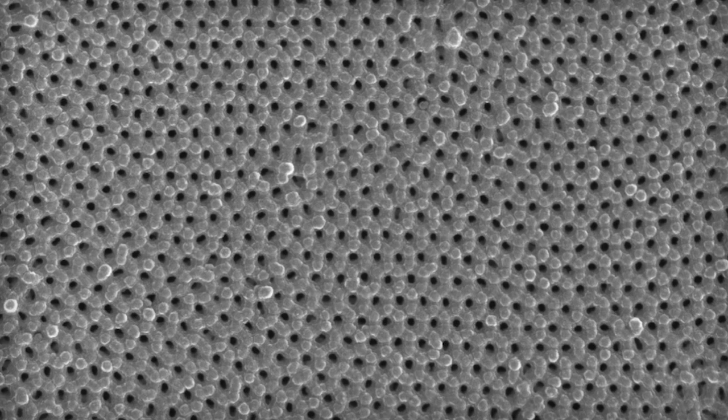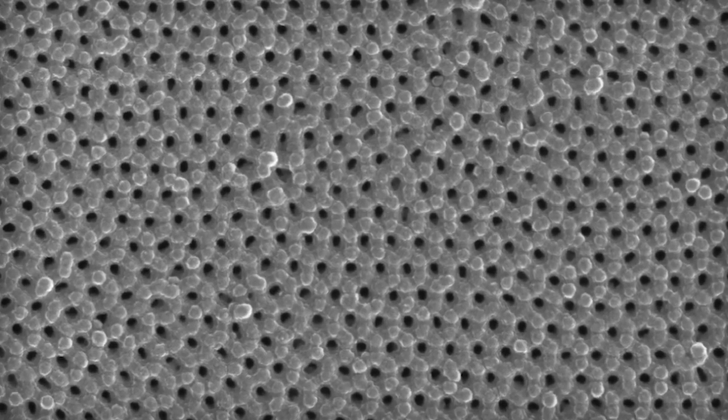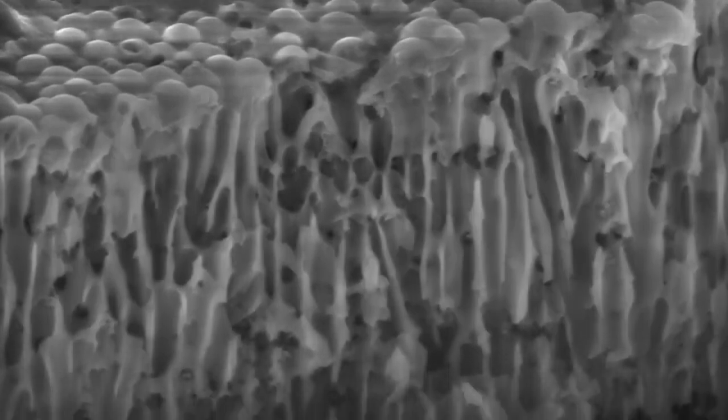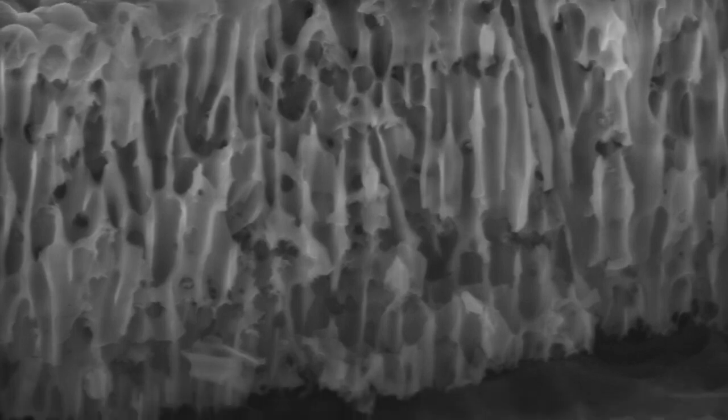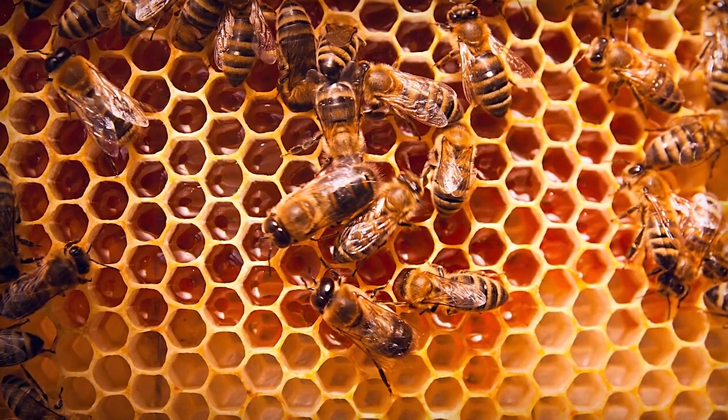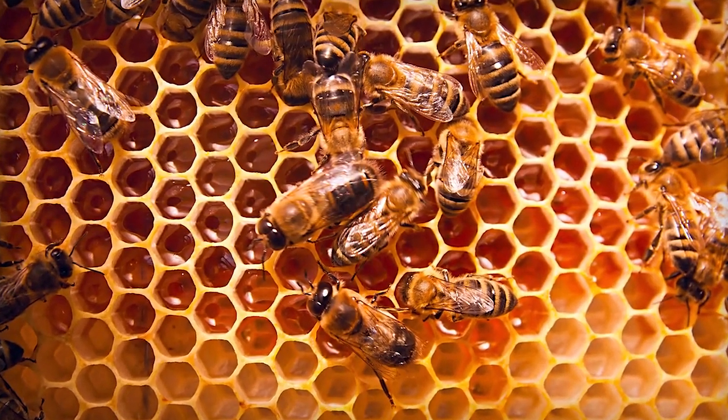The structure of porous anodic aluminum oxide is hexagonal and is characterized by a large number of mutually parallel pores extending through the film to oxide-metal interfaces, where each cylindrical nanopore is closed by a thin barrier oxide layer with hemispherical geometry. Each pore and the region surrounding it comprise a hexagonal cell. These cells are self-organized in the form of a hexagonally close-packed structure, just like a honeycomb.